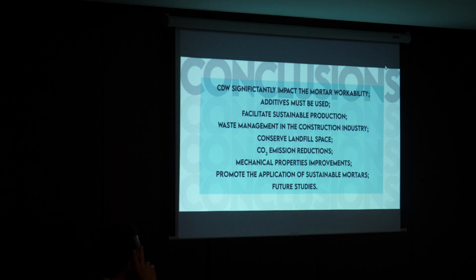To conclude, we can say that the bad part of using the construction demolition waste sand is that it significantly impacts the mortar workability, and we have to use an additive. And like I said before, for cases like the 100% replacement rate, there was a high value to use. Usually in cementitious materials we use 1 or 2% of superplasticizer additive, not something like 7 or 6.5%.